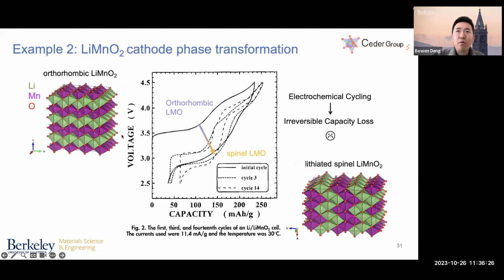The next example is about lithium manganese oxide cathode material. Lithium manganese oxide cathode material is known to undergo a phase transformation from the orthorhombic phase, shown on the top left, to the spinel phase, shown on the bottom right. This happens spontaneously through electrochemical cycling, which leads to irreversible capacity loss that essentially prevents its usage as a commercial high-capacity cathode material.